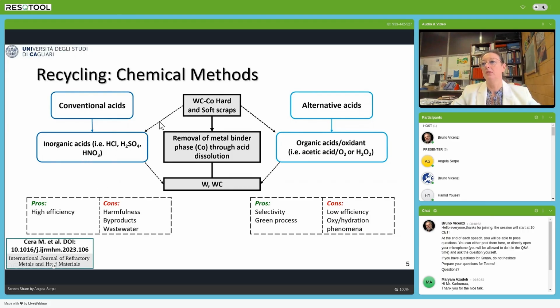As Teemu anticipated, this kind of approach is selective, so we can reuse to a certain extent the tungsten carbide that remains unreacted, but the use of strong acids, in particular strong oxidizing acids like nitric acid or sulfuric acid, often makes an oxidation on the surface of the material. So this oxidation on the material requires a further reduction step, a thermal reduction step, to obtain again the tungsten carbide cobalt material with characteristics that are suitable for hard metal production.